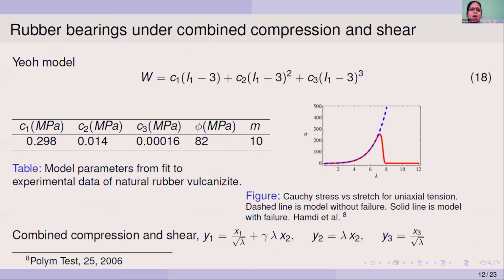So next we analyze the onset of localized cracks in rubber bearings under combined compression and shear, as the rubber bearings that are used for seismic isolation are often compressed by the weight of the supported structure and are also prone to large shear deformations during earthquakes. In order to describe the intact material behavior, we use this incompressible model for the strain energy density W, and we obtain these model parameters by matching this model response to the experimental data of natural rubber vulcanizate in uniaxial tension as obtained by Hamdi and his colleagues.